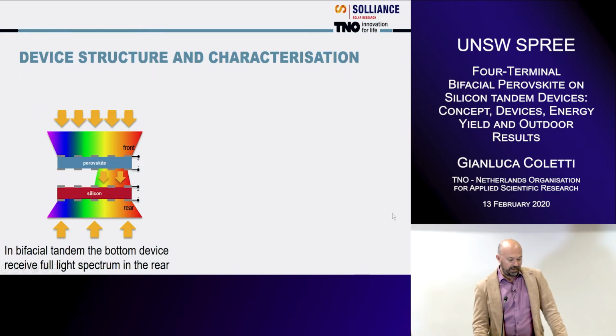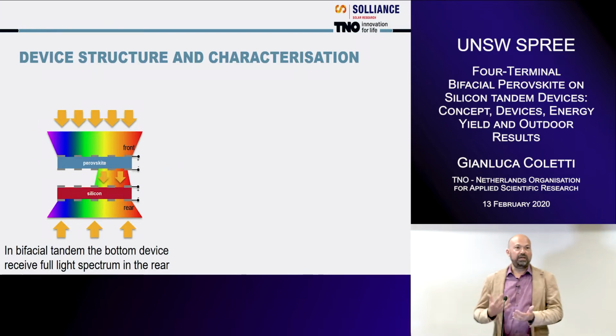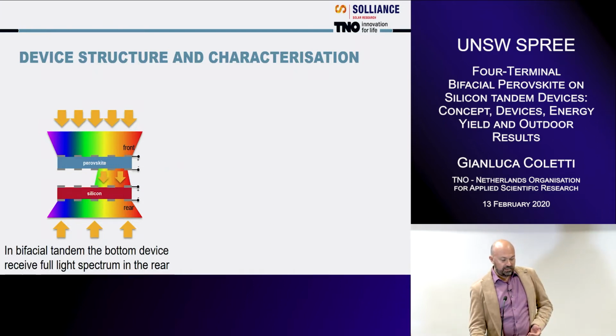As you see here, you have the perovskite, and that's absorbing the blue and the UV and the visible part of the spectrum of the light, and is transparent to the near infrared, and that's absorbed by the silicon device. Now, when you include the effect from the rear side, note the important thing is that from the rear side you have the full spectrum. So in practice, you can design a bottom device that is not so responsive to the UV in the front, but then in the rear side you still want this feature.